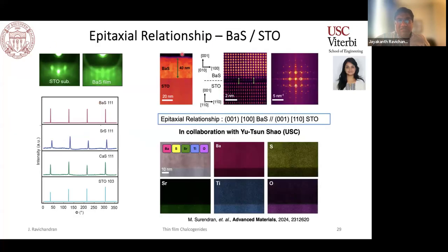So what's the epitaxial relationship for barium sulfide? The choice of substrate we picked here was strontium titanate. It's a perovskite, rock salt on perovskite, but it turns out you still have some reasonable epitaxial relationship. You can see that the interface is much nicer compared to what we saw in barium zirconium sulfide.